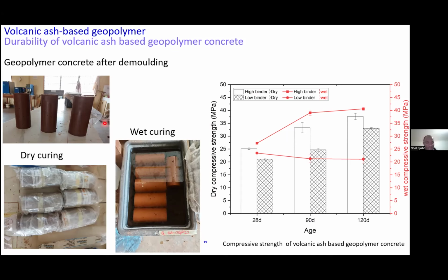So here we have this concrete block that we have made, and here what I did is I cured them in different ways. A dry curing, as you see here, just mix them, and a wet curing. This is because we all know that in Africa, the main weather is rain and sun. So it is either warm, or there is too much rain. Because of those changes of wetting period and drying season, we need to make sure that the material that we are developing can sustain that environment.